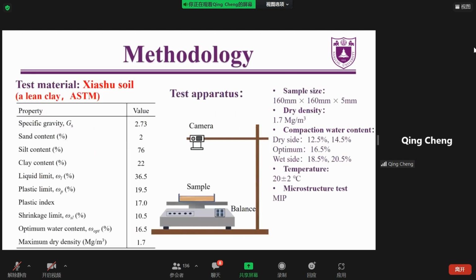The testing material is Xiashu soil taken from Nanjing, China. According to the ASTM standard, it can be classified as a lean clay. In this study, 5 soil samples are compacted with 5 different water contents. 2 samples are compacted on the dry side, 1 sample is compacted at the optimum water content, and another 2 samples were compacted on the wet side. After compaction, the soil samples were subjected to saturation and then the drying process.